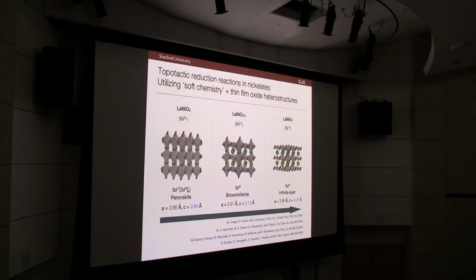And by flowing hydrogen gas at relatively low pressures, they suggested there was a sequence of reduction, or topotactic reduction, reactions where essentially you pull out a row here and here and here and here of oxygen to make an intermediate phase that has one more d electron, one less oxidation state. And if you go further and pull out the other row of oxygen, you get this infinite layer structure. And at some point at the end, I'll explain this terminology, hopefully.